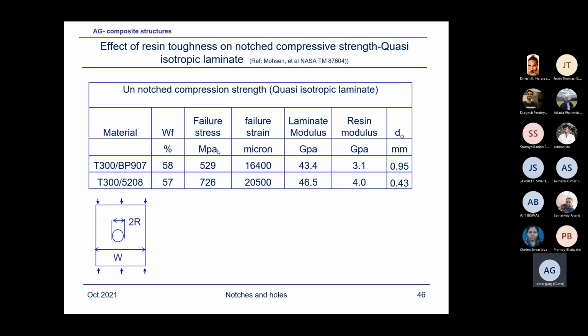Effect of resin toughness on notch compressive strength, quasi-isotropic. Now, I've just put some data for T300/BP907, which is a toughened material. The fiber is the same in both. This is brittle material and this is toughened material. And you see here for the quarter-inch hole, I think it's 6.4. I'll check up, but the diameter of the hole is 6.4 millimeter, quarter-inch, I think, if I'm not wrong.